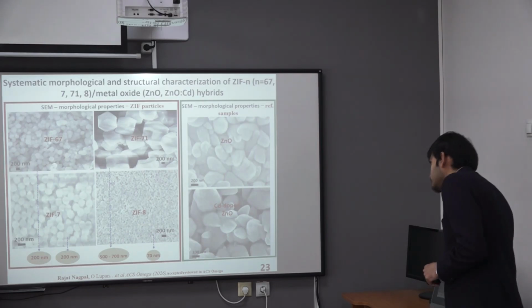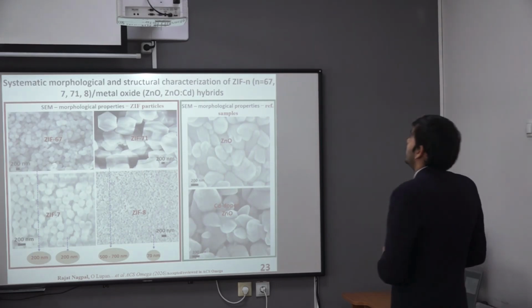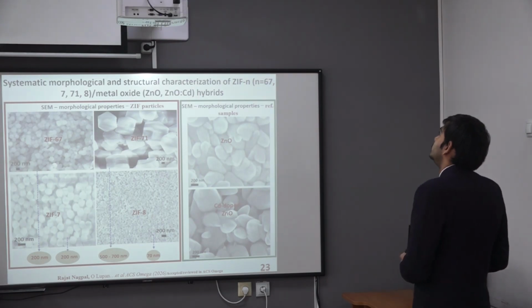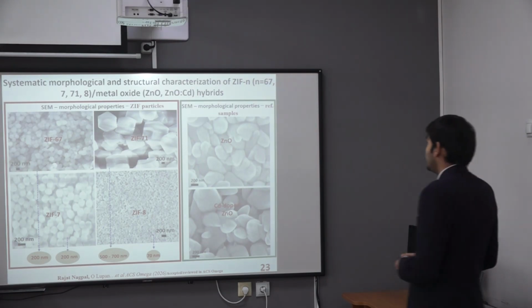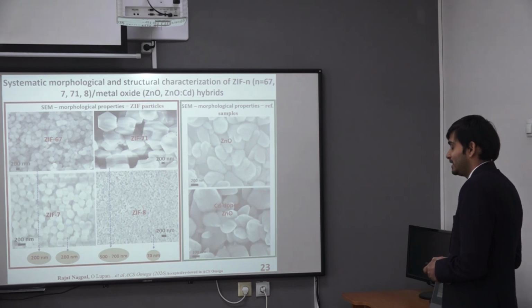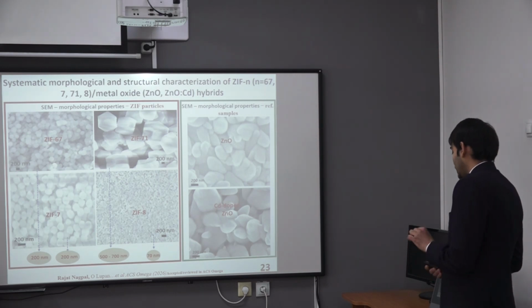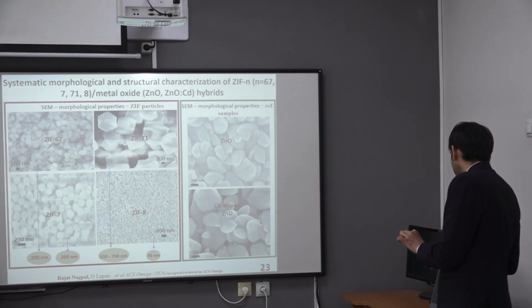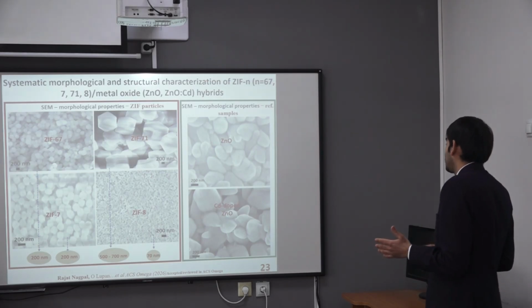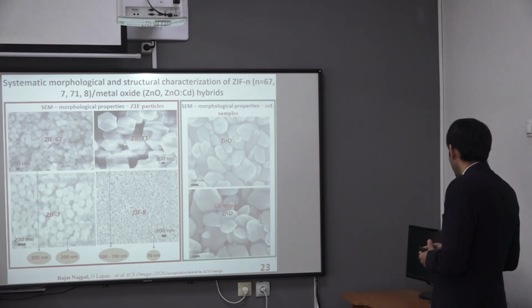And how could you avoid the charging? What would be a possibility at the end to avoid it? Do you have any ideas? Yes, one thing we tried, because we made a lot of SEM measurements, was to use conducting adhesion tape so that we can ground the charges. For example, putting a bit of conducting tape on the surface of this hybrid system and connecting it with the ground. We tried this, and definitely we saw some improvements.